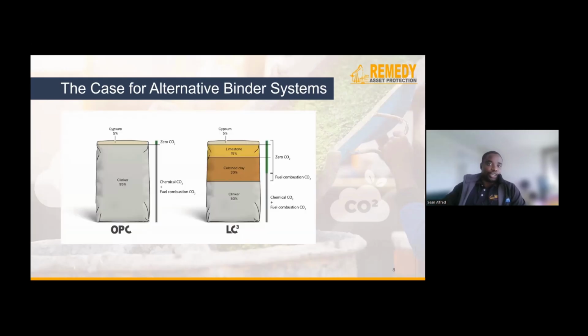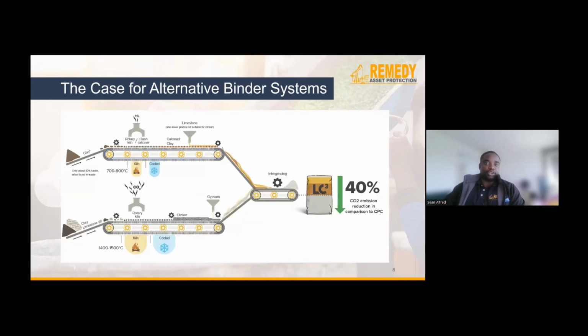Right, so LC3 contributes to the reduction of carbon emissions mainly by substituting the energy-intensive clinker content. One innovation, using this example I've put on the screen, is to use 50% of the clinker content from normal OPC with 30% low-grade kaolinite clay, 15% limestone, and 5% gypsum. What that does is the lower use of the clinker content reduces the carbon emissions released during production processes by up to 40% compared to ordinary Portland cement.